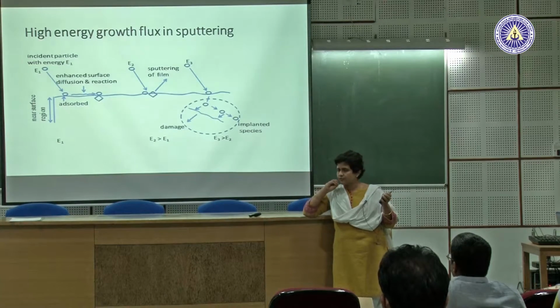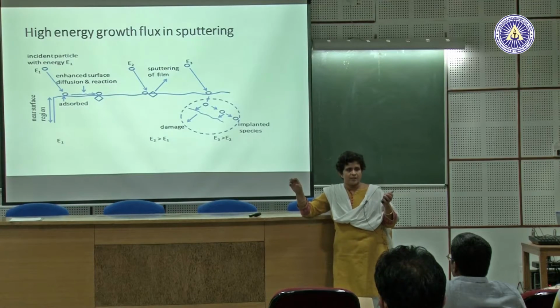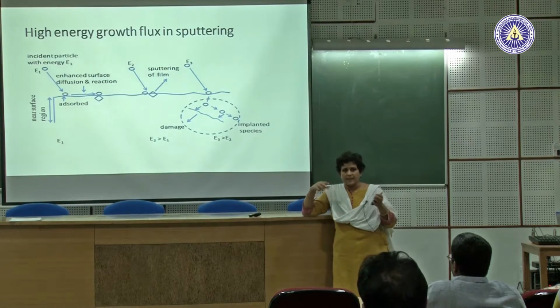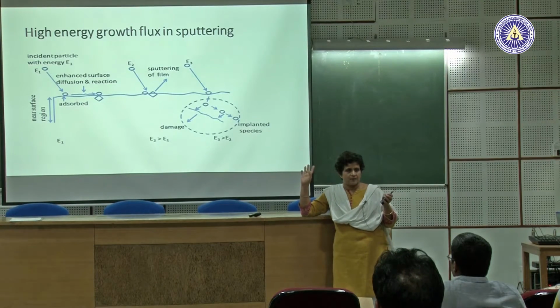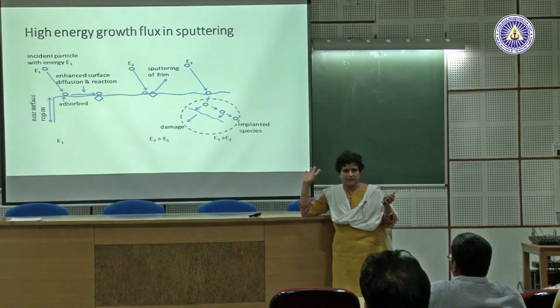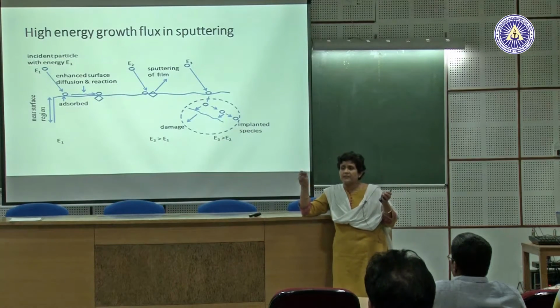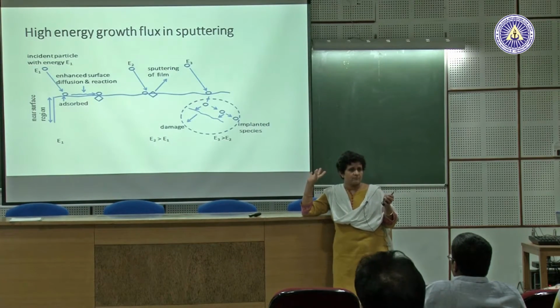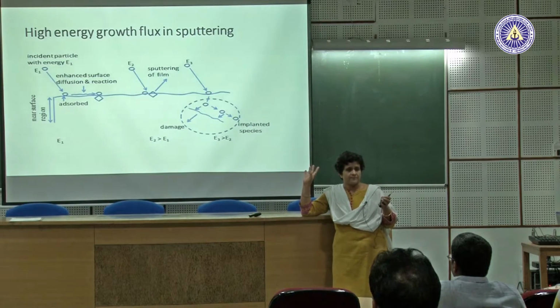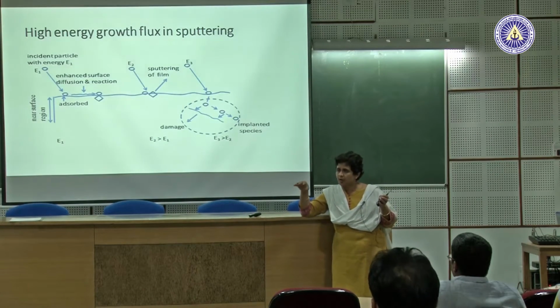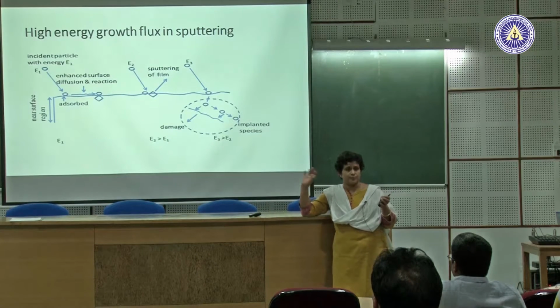If we don't allow them to find a good place where they should get deposited, if wherever they hit, they just deposit there, randomly they are coming. What would be the end material? It will be amorphous material, with lots of cavities and voids inside. It will not be a good density material. So this surface diffusion is very important for creating a dense material, a dense film.